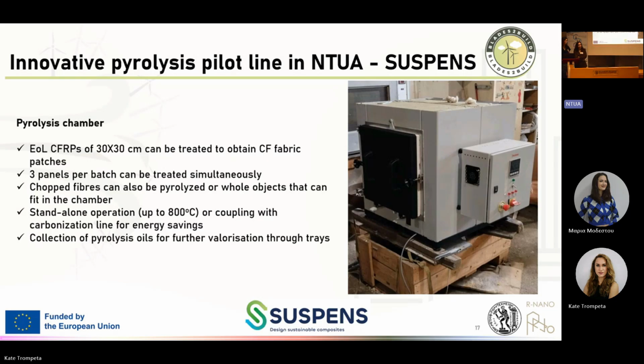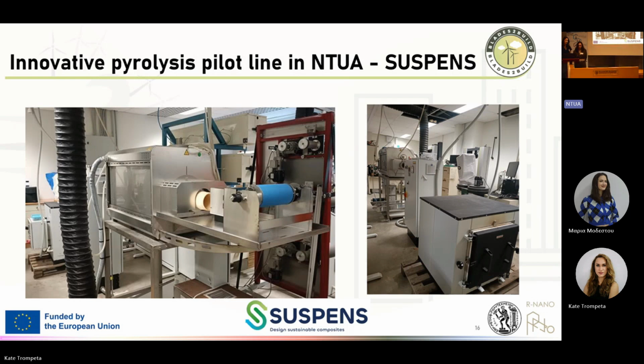A chamber like this costs up to 25,000 euros. Your reactor costs, I think 60,000 was the small one, 80,000 euros, and small for an industry. So I guess that for solvolysis, the high pressure reactors are more expensive than the furnaces used for pyrolysis. And imagine that the furnaces used for pyrolysis do not go to very high temperatures. So in general, they are low-cost equipment in comparison with your case. There's also the energy needed to operate both systems. That's why we invented this combined process with the carbonization of carbon fiber production.